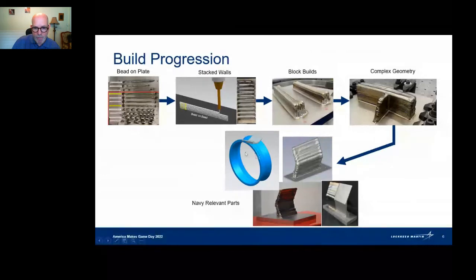We got into, as I mentioned, this annular, what we call an annular ring. What we did before that ring was we took and just extruded that cross section and built a straight angled wall out of that cross section, and then had that machined to show that we had built that properly to where the part could be extracted or machined from the build that we had conducted.